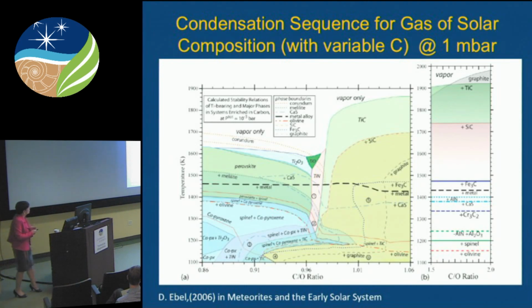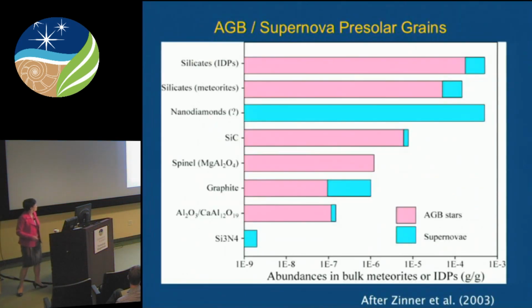All right, so what do we expect to condense in the solar system? We use equilibrium thermodynamics as our guide. You have to start with a gas of some known composition. Typically, we model gas of solar composition because we know the relative abundance fairly well of most of the elements. For a carbon-rich C to O ratio, or close to carbon more abundant than oxygen, you can form carbonaceous phases. So starting from high temperature, working your way down, you're initially likely to see titanium carbide, then silicon carbide, then you can get metal, calcium sulfide, and so on down to graphite or so. So I'm going to focus mostly on carbonaceous materials for this talk, so we're on that side of the phase diagram.